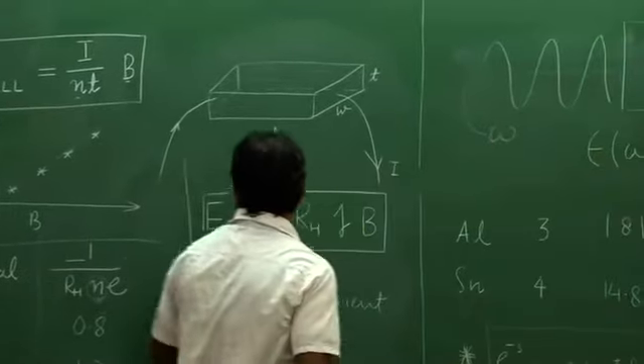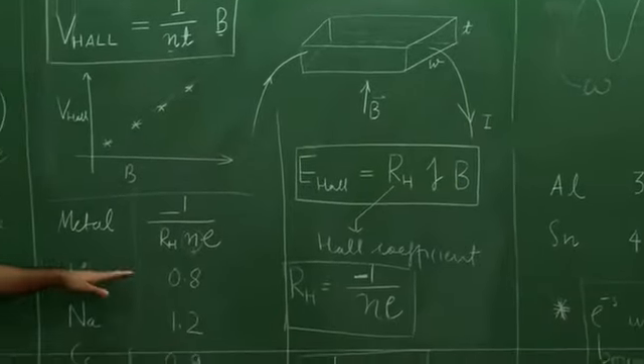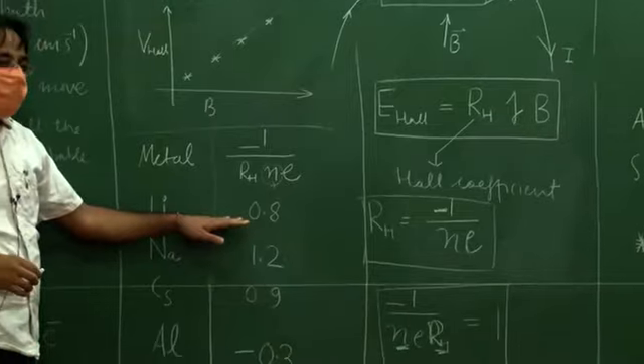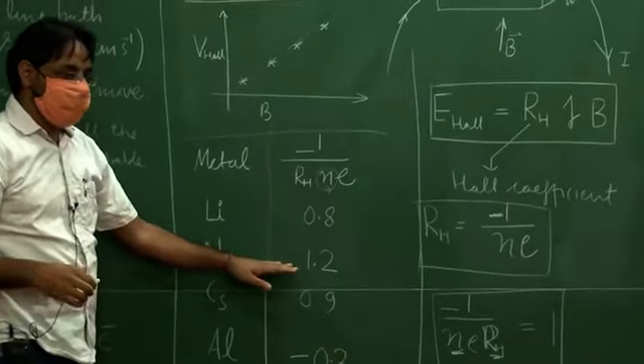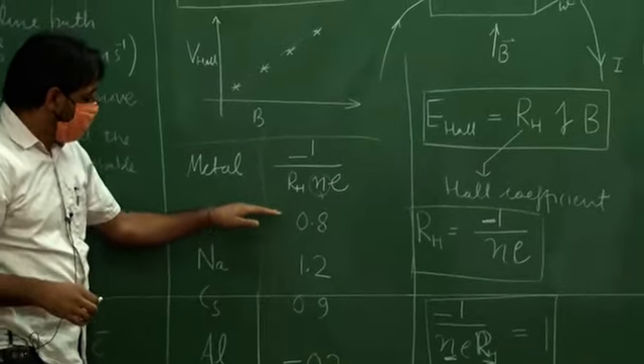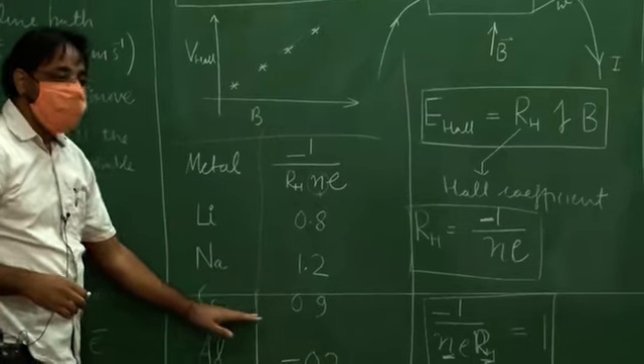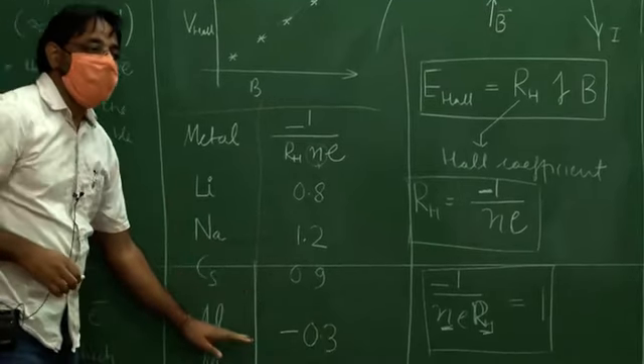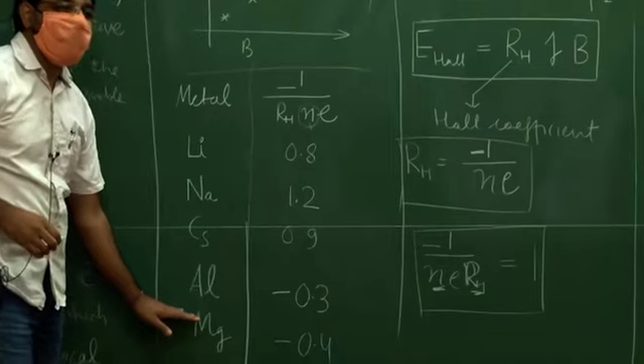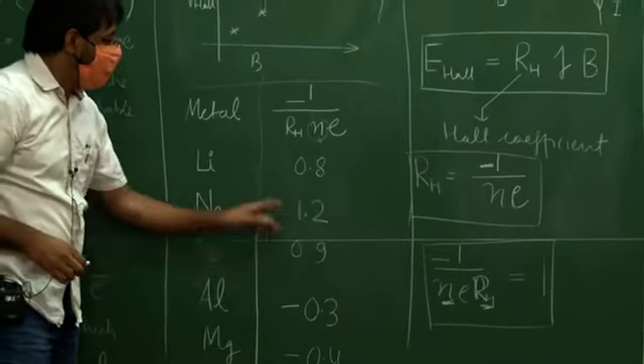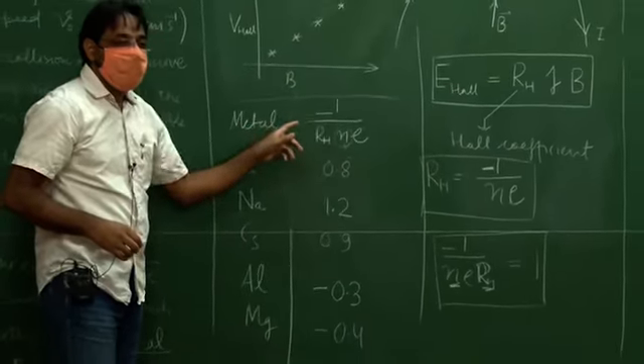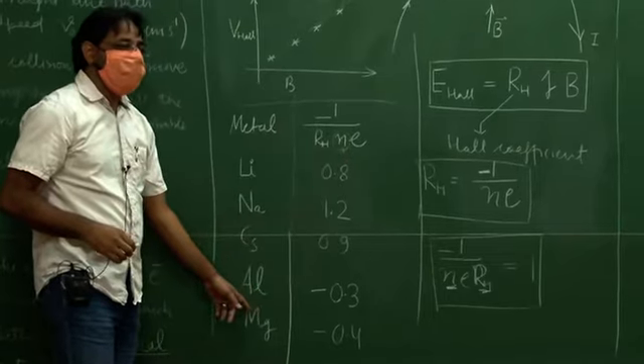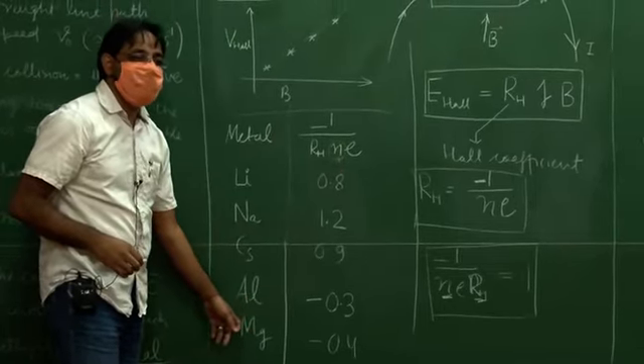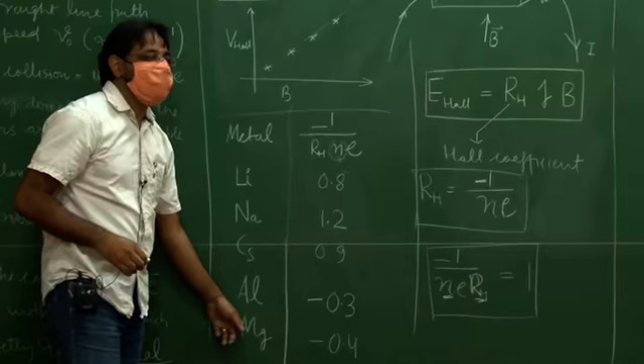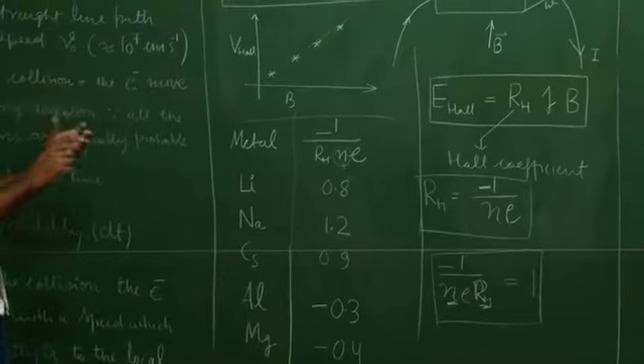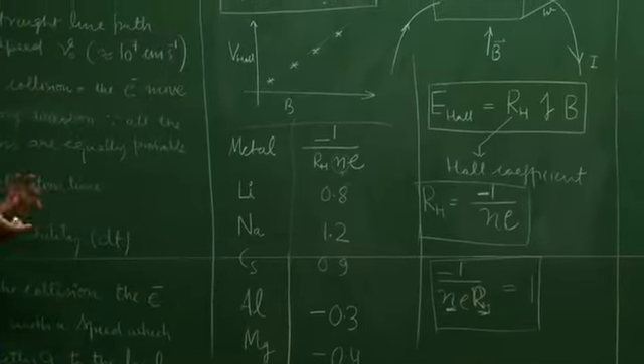And by the way, even here, Drude's model did a fairly good justification of the carrier concentration for various metals. But then it failed miserably. I mean, it not only gave a very small value for something that you expect to be 1, but also gave an opposite sign. I mean, this opposite sign is quite serious actually. You cannot simply understand it even if you tweak Drude's model in this way or that way.